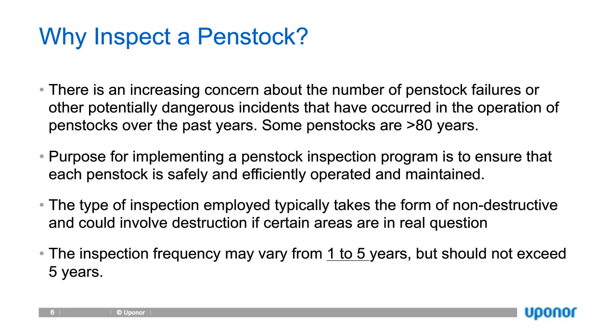One being, typically on an annual basis, you should be walking the line, doing a visual inspection, and then later on, from 2 to 5 years, you should be doing more of an integral inspection that could employ equipment. So that is doing typically wall thickness measurements within steel pipe, and if you're using pre-stressed concrete cylinder pipe, which is PCCP, the acronym, you may want to be measuring to see if there's any broken wires or pre-stressed wires within the concrete pipe. If you have wire breakage, as you're aware, you can lose integrity. If I have wall thinning up to a certain percentage, I could have a rupture within the pipe.